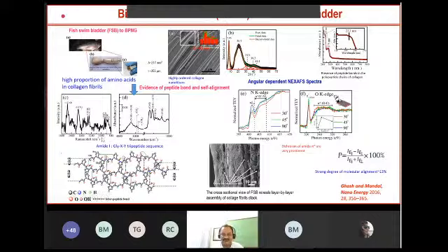So you see the photon energy on the x-axis. One can change the x-axis here, and one can measure the electron yield here. Collagen consists of nitrogen, oxygen, these kinds of elements, and this is angular dependent near edge X-ray absorption spectroscopy. In short, I can say that if there is a difference, you see three different signals at three different incident angles, it means that it has some sort of orientation. And in this particular chemical structure, you can see again the dipoles are there, and some interpeptide bonds are connected with these dipoles.